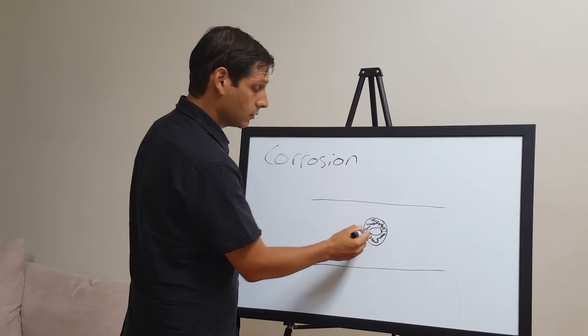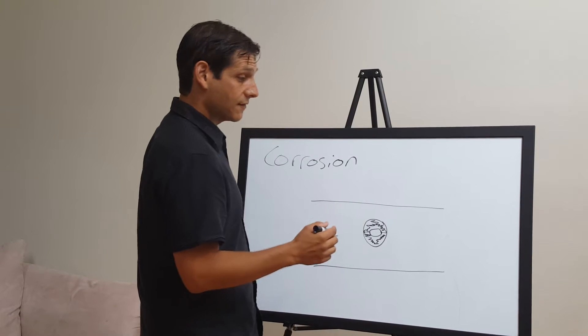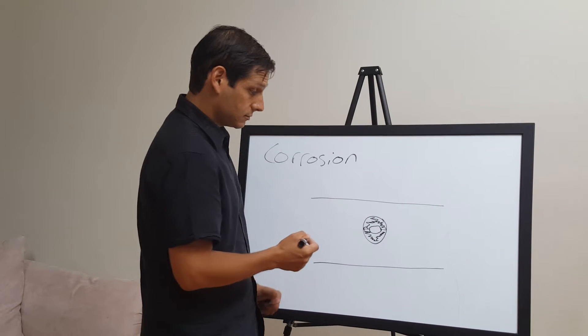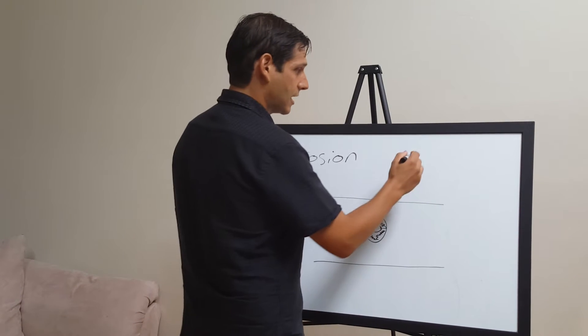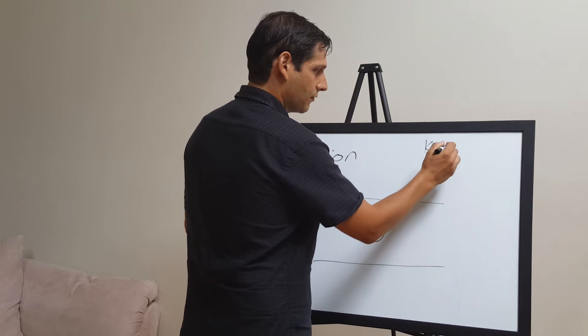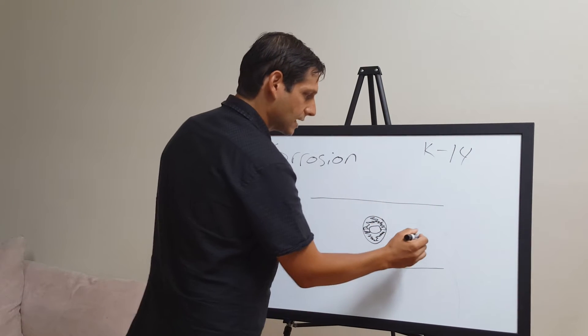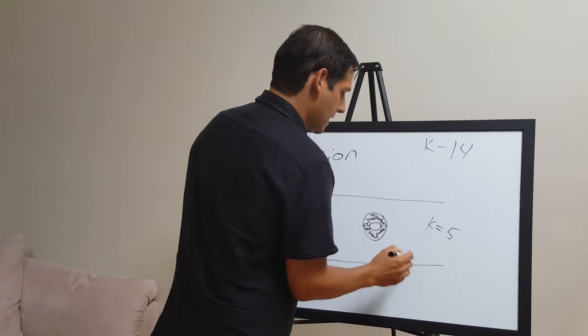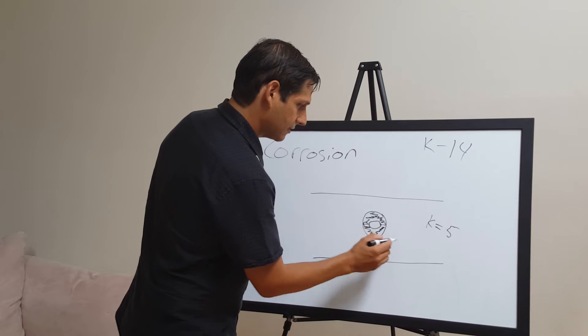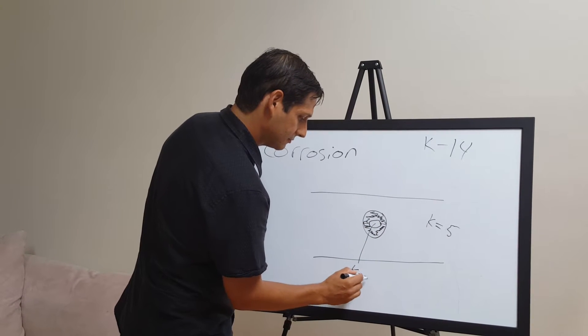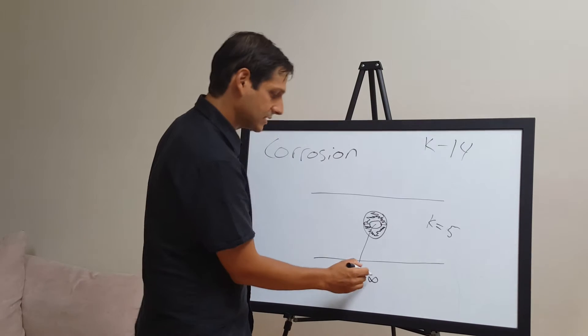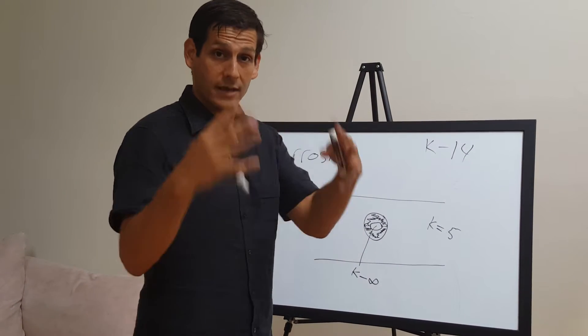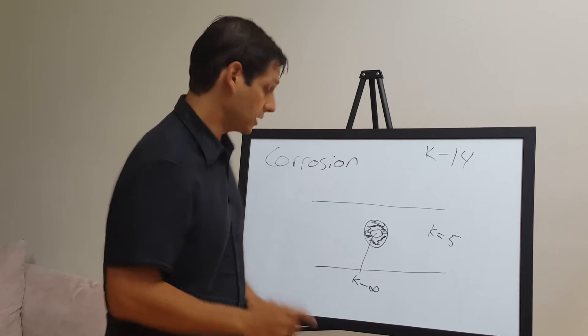Steel or highly conductive metal tends to have a very high dielectric constant, where corroded steel iron oxides actually have a dielectric constant of about fourteen. Concrete has a dielectric constant of about five, and steel will tend to have it at almost infinity. That's debatable—maybe there's nothing that's actually infinity—however, the more polarizing the metal is, the closer it gets to infinity.